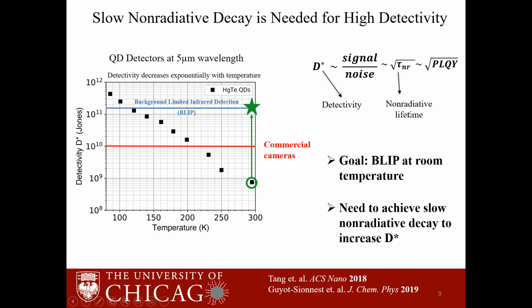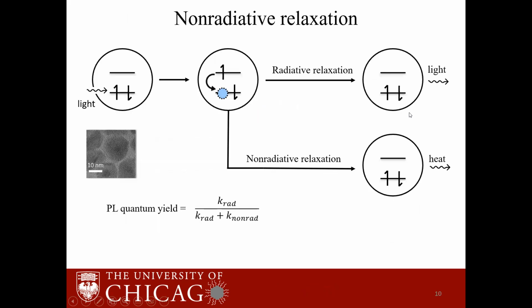But for this slide, we can see that the detectivity goes as a square root of the non-radiative lifetime or a square root of the fluorescence quantum yield. The current mercury telluride quantum dots have a non-radiative lifetime of the order of hundreds of picoseconds, which corresponds to quantum yields of a few times 10 to the minus 4. So for us to reach our dream, we need to find a way to reduce the non-radiative rate by 4 orders of magnitude. So in this slide, I will talk to you about what we mean by non-radiative relaxation.